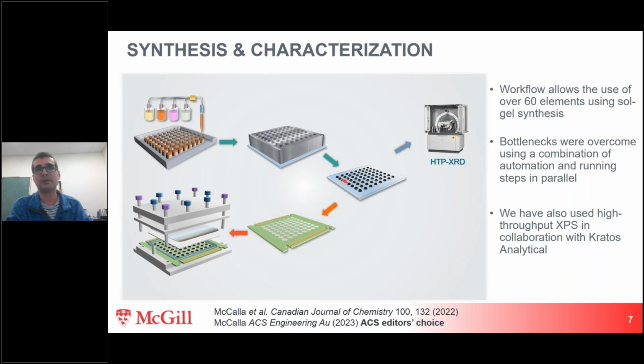So we mix our cathodes here with carbon black to make them conductive, and also we use a binder so they don't detach from the contact here. And then we close up the battery, so we put electrolyte on the separator, and we have one piece of sodium on the other side. So we actually end up with 64 batteries all connected in parallel, and that means that we can control the voltage. This is why we do cyclic voltammetry. So we sweep the voltage and measure the current, and we can do it on all 64 at once.